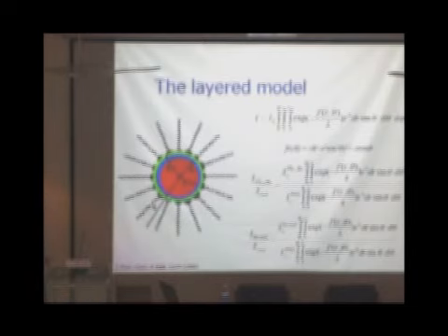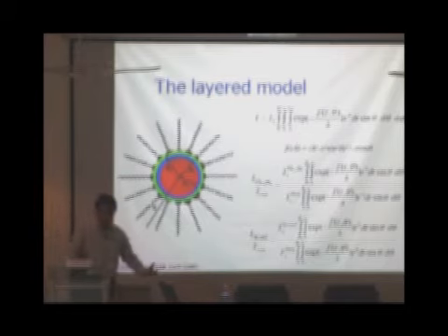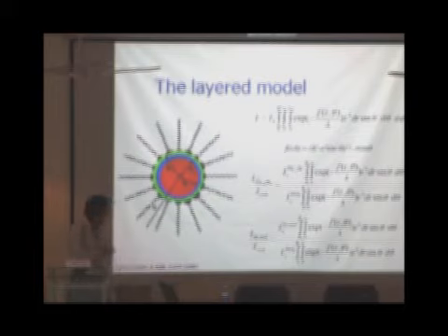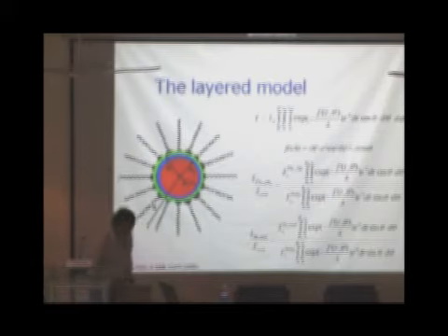Okay. So the model comes out to be that you have a core over here, which is very good crystalline lead selenide, and then you have a non-stoichiometric shell of selenium present on top of it. And from the analysis, as the particle grows, this non-stoichiometric shell keeps on growing. And subsequently, the fluorescence intensities keep coming down as a function of size.